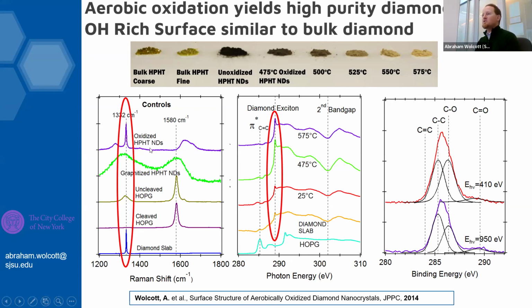Here's a single crystal diamond slab. Here's our oxidized HPHT nanodiamonds. There are some additional features on the left-hand side that we believe are caused by Pandey chains or the reconstruction of the diamond surface. With the XAS, we were able to see the diamond core hole exciton for the first time with nanoscale diamond, and that's at 289 eV. The main idea, though, is that alcohols are the most predominant surface group on our diamond, in contrast to detonation diamond, which people would say usually has carboxylic acids. And we can use XPS to reinforce that and show that mostly single carbon-oxygen bonds and very few C=O bonds are on the surface.